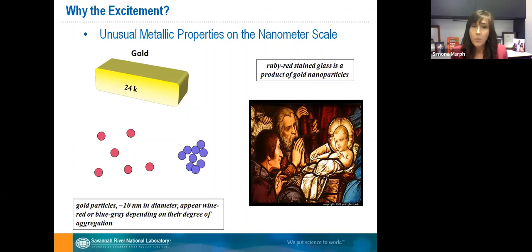So what you see here, of course, once you get to the nanometer scale, you can get these beautiful ruby red color solutions. This was discovered since ancient times, and you can see them in Europe in the stained glass windows. They are actually gold nanoparticles, golden spherical nanoparticles. Many times people ask about the gold, so can you comment on the stability of these nanostructures? I always refer, well, go to Europe and see them. They're still there in the stained glass windows in churches, so they are quite stable.